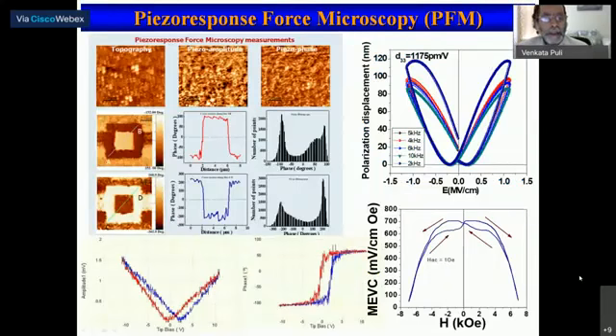We obtained excellent PFM behavior, with ferroelectric, piezoelectric, and piezomagnetic behavior for these films. You can see from the amplitude and phase images the bright and dark contrasts, which also confirm the square patterns shown here. Perfect square patterns were recorded from the PFM measurements, and at the nanoscale you can see the hysteresis loops for both amplitude and phase, which show the perfection of these films. We also made polarization displacement measurements with large values of 1175 picometer per volt. For multiferroic materials, magnetoelectric coupling is most important for applications, and these films have shown excellent and extraordinary data even for the magnetoelectric coupling.